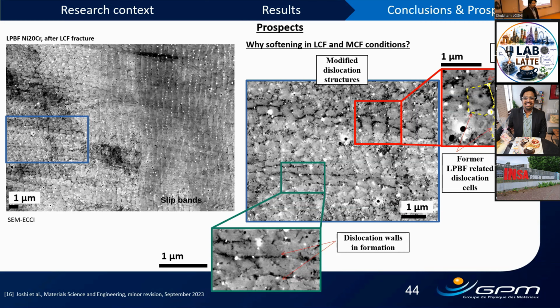I will start my questions chapter by chapter. Firstly, I have a question concerning the chromium-rich precipitation. You talk about the localization of this precipitation in the dendritic cellular walls. But when I see the EDS analysis, I see that the wall of the dendritic cells is rich not just in chromium but also in nickel. Do you have an idea about which phenomenon leads to having chromium and nickel simultaneously in the walls of the dendritic cells?